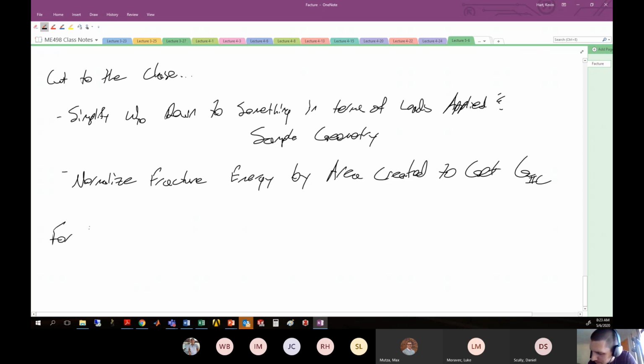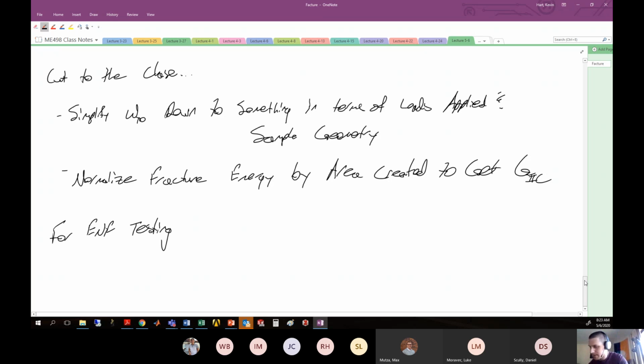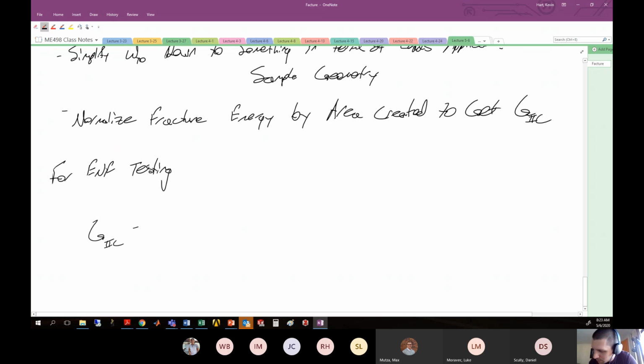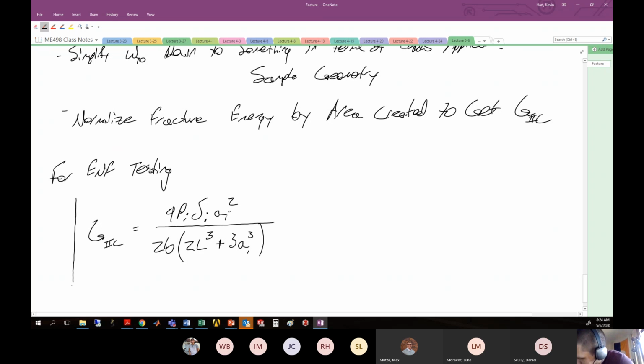And that is for edge notch flexure testing with the geometry described above. We have that G2C is equal to the following. Here we have 9 P_I delta_I a_I squared over 2b, or not 2b, 2L cubed plus 3a_I cubed, plus... And there's your general expression for critical strain energy release rate in mode 2 with an edge notch flexure sample. And this is good for 3 and 4 ENF.